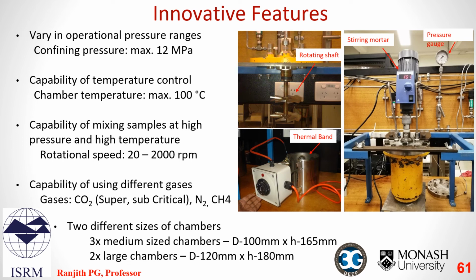Some of the unique and innovative features of this setup are an extensive range of operational conditions. We have confining pressures up to 12 MPa and temperatures of up to 100 degrees C for very long reaction times, for example, from a few hours to a few years. We can use different gases for injection, for example, carbon dioxide, nitrogen, or methane, or use other types of liquid having both high pH and low pH, including lixiviants used in in situ mineral leaching.